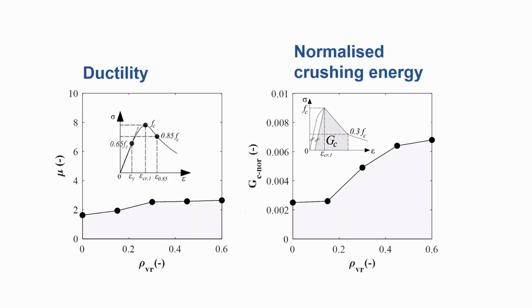But then when we look at things like ductility, for instance, which we got from the stress-strain response as the ratio of the strain corresponding to about 85% of the compressive strength on the descending branch to the strain corresponding to about 65% of the compressive strength on the ascending branch, we see as the rubber content increases, the ductility of the concrete increases. And we see the same when we look at the normalized crushing energy.